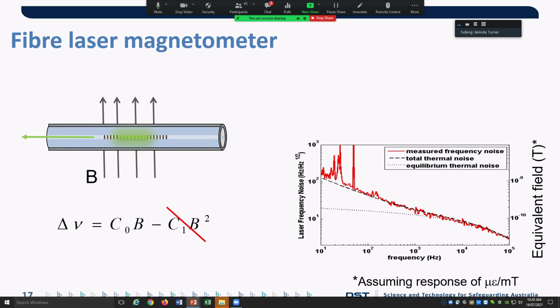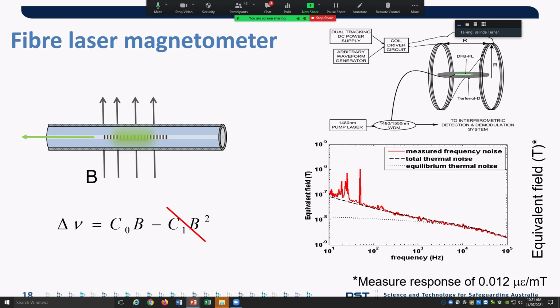And I predicted, based on what I know from the minimum detectable strain of fibre laser sensors, that I would be able to get, say at 1 kilohertz, a magnetic sensitivity of about 10 to the minus 10 Tesla, 100 picotesla, which is actually quite good, getting into a regime which is useful for detecting submarines. But when we actually did the experiment, we were about 100 times less sensitive than that.